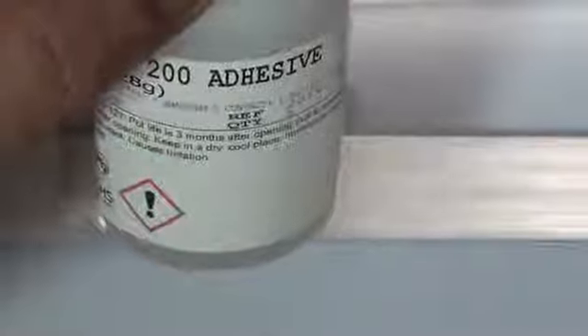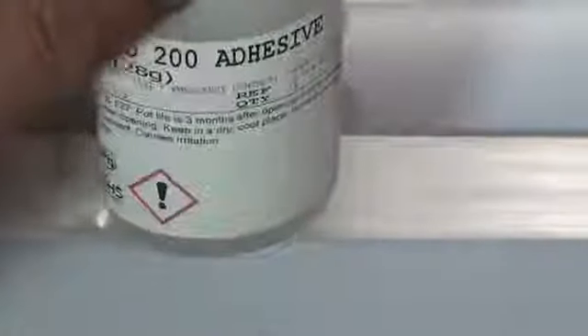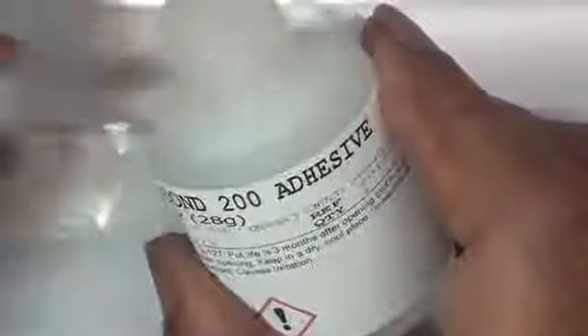The normal adhesives that are available in the market are only required to stick two pieces together, and there's no special requirement for that to be really very strong. So the chances are that if we get a commercial adhesive and try to bond a strain gauge, we will not get sufficient adhesion between the gauge and the component to really measure strain accurately. It's such a critical component. This is the material that's going to transfer the strain, the surface deformations, from that aluminum to the sensor that's going to make the precision measurement. So it's very much worth it to have a gauge adhesive that's tested, has specifications for strain measurement, and we can rely on that to transfer strain so that we can arrive at an accurate measurement later.